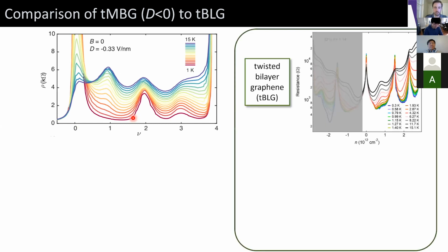It turns out that we've seen similar things in twisted bilayer graphene as long as we go to samples that are not exactly at the magic angle, or in samples that have electrostatic screening, such that we can marginalize the effective correlations. And I should point out that Leo has done really a fantastic experiment in this regard. And so what we see in this case is, okay, well, there's a correlated insulating state here, but the ones at quarter and three-quarter filling are also these similar correlated metallic states, where we see these clear bumps at high temperature and they get smaller, or at least they're not insulating as we lower the system's temperature.